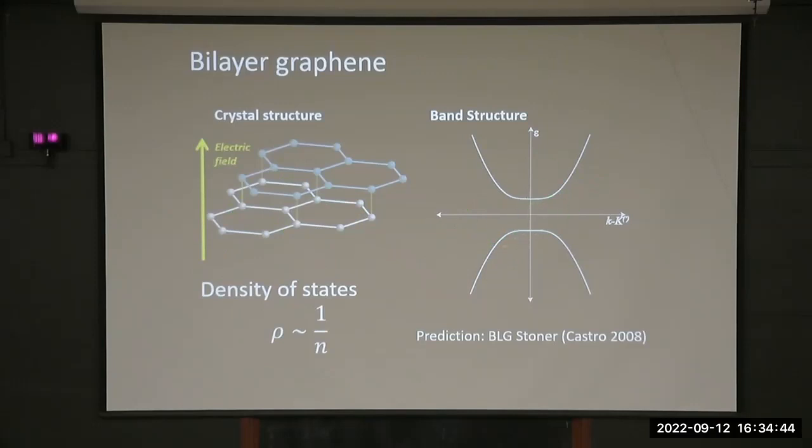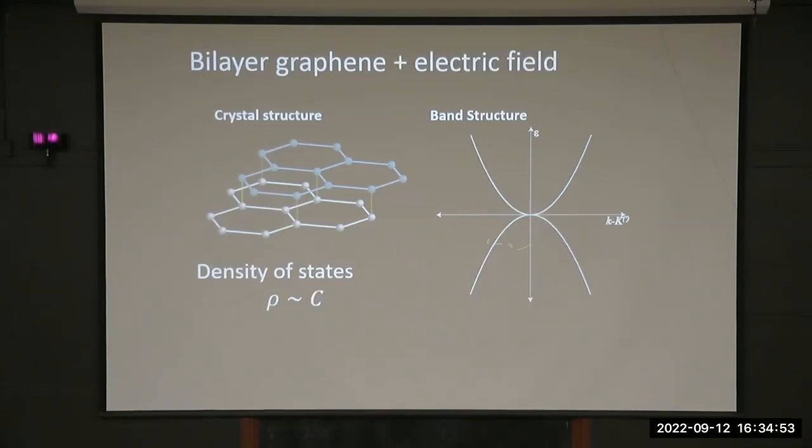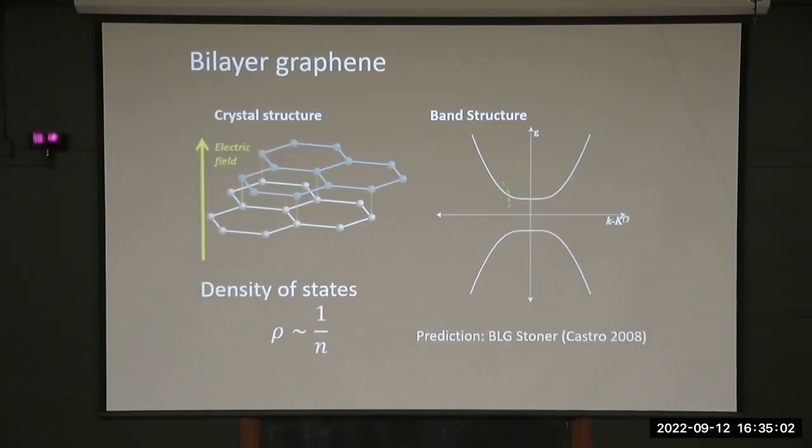that energy gap at charge neutrality is a little bit unusual, because normally in semiconductors, you have some minimum, and that minimum is quadratic, and that gives you a constant density of states in 2 dimensions. But here you started with a quadratic minimum because of the details of the band structure of this material. And when you apply an electric field, you end up with a band structure that is a quartic minimum in energy. It goes basically like p to the 4th. And if you think about p to the 4th dispersion in 2 dimensions, it turns out you get a density of states that actually diverges as you go to low density.